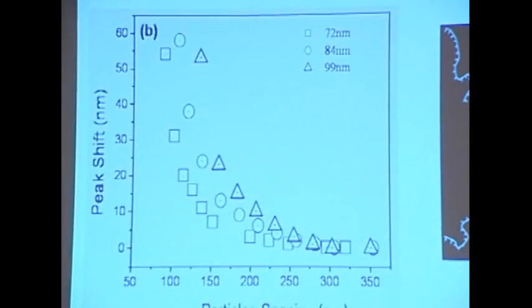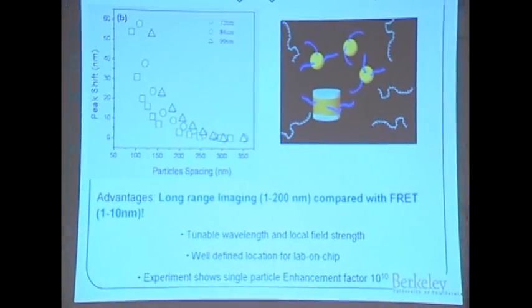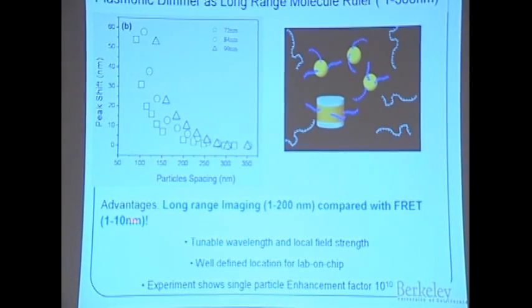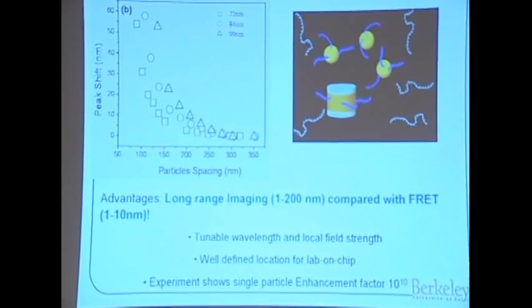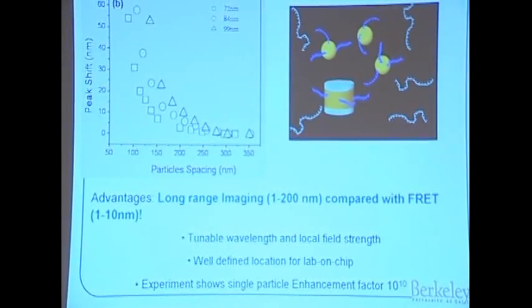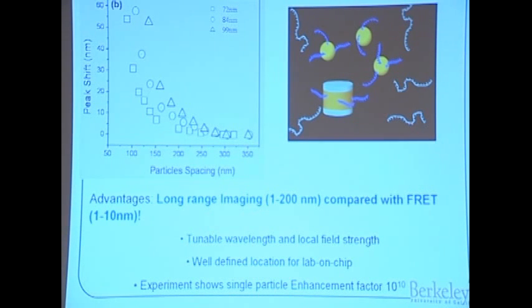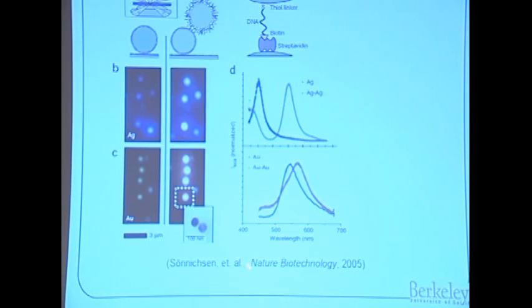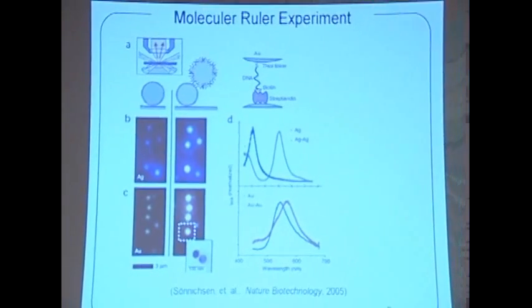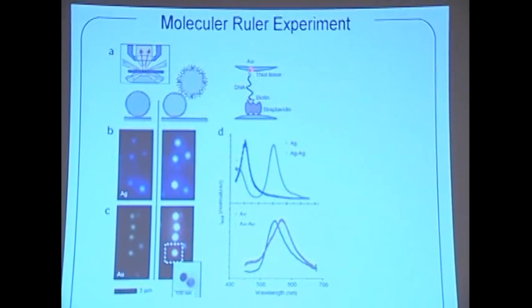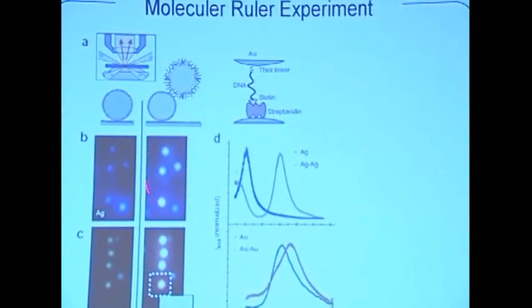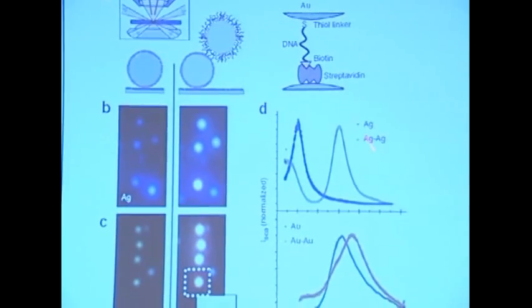That is interesting because FRET technology was originally invented at Berkeley by Shimon Weiss. It is a very interesting technology today to look at biomolecular distances between 1 and 10 nanometers. But above 10 nanometers it is very hard to achieve this electronic resonance transfer. So this provides a possibility to extend that all the way to about 200 to 300 nanometers, which a regular optical microscope can pick up. This dependence provides a possibility for long-range imaging of distance. About 2 years later, a group in chemistry here successfully used DNA of different lengths to demonstrate that it can indeed be used for biological imaging. You can look at the different colors, essentially the peak shift, and tell the distance, the DNA length.